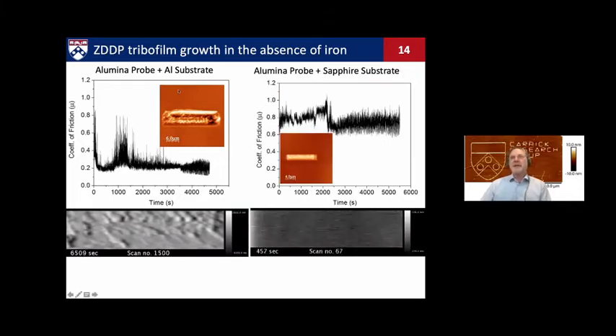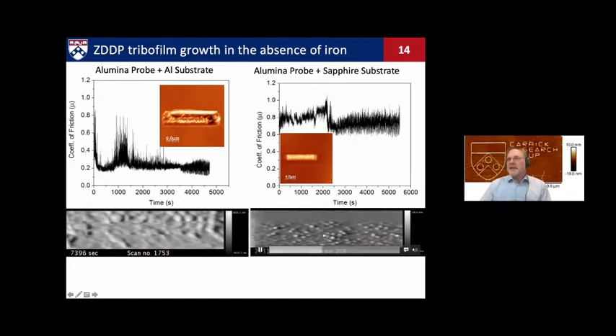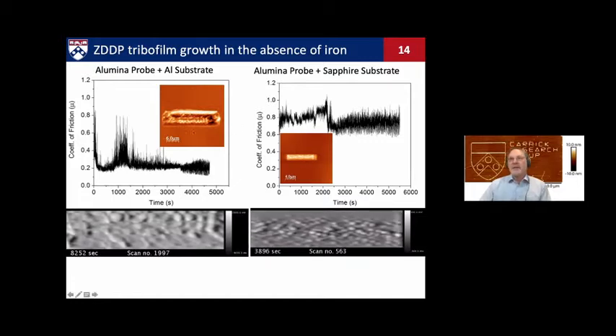But clearly, you see these patches that are growing. These, we believe, are these ZDDP-based tribofilms that have finally grown on aluminum after struggling to do so at first. We see them on aluminum oxide as well. Again, we don't see much growth at first, but after some time, eventually we start seeing the nucleation of some pads, and then a stable tribofilm grows. And it only grows in the region where we've been sliding. These colored AFM images are zoom-outs from the sliding region.